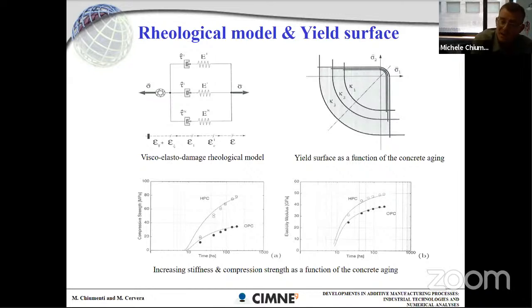What you typically need to get from the experiment are curves like this one, where you can see how the strength is increasing with time and how the stiffness is increasing with time. So this will be the main input for the software. So instead of having a temperature dependency, you have a time dependency according to the aging of the material. At the end of the day, we would like to use exactly the same framework that we have for